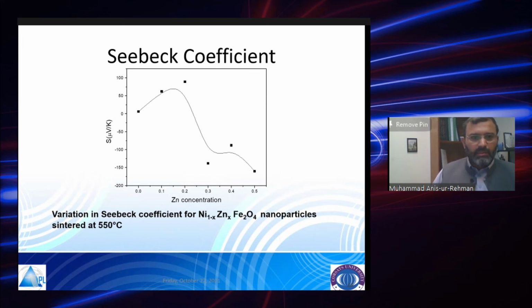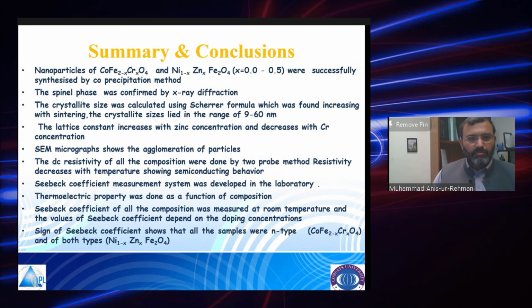In the case of the nickel zinc ferrites, we see an interesting thing, that in this material, as we increase the zinc concentration, we got both p-type and n-type material within the same family of ferrites. So nanoparticles of cobalt ferrites and nickel zinc ferrites were successfully synthesized, all with the spinel structure, and the lattice constant increases with the zinc concentration. SEM micrographs show agglomerated particles. The resistivity measurements were done by the two-probe method. Thermoelectric properties were studied as a function of composition. The Seebeck coefficient shows that all the samples were n-type in the case of cobalt ferrite and of both types in nickel zinc ferrite.